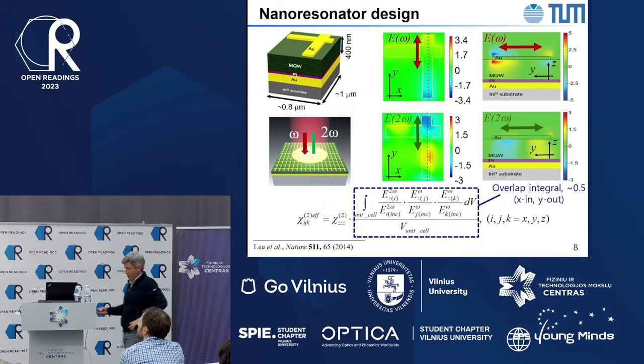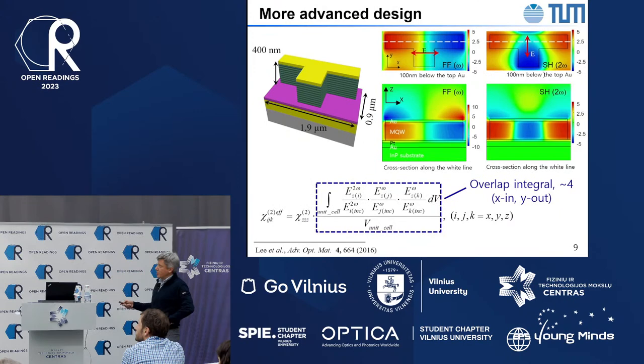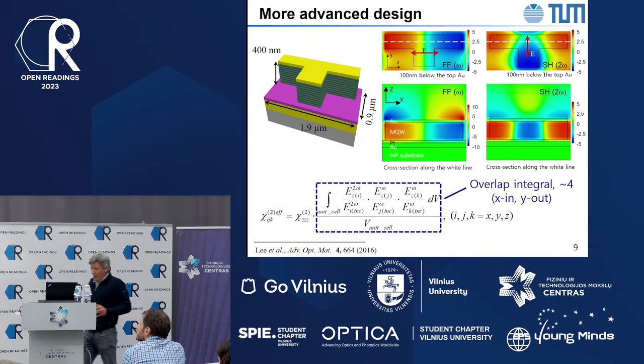And in the future, we of course improved the resonator design, so these are more improved ones with the T-shape, and now we etch the semiconductor heterostructure. Now you can see much stronger field enhancement and much more uniform distribution of the electric field at omega and 2 omega, and now this overlap integral is about 4. So how well does this thing work?